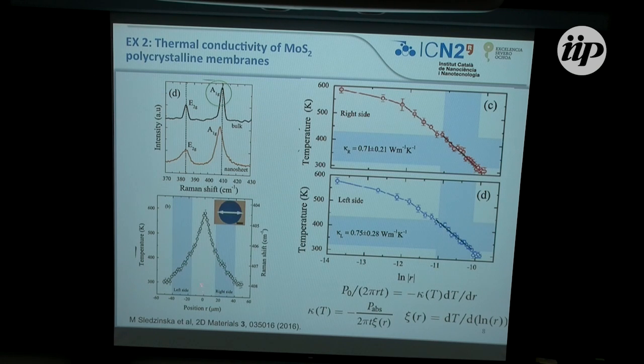And it gives us this temperature field as a function of a point across the membrane, basically going up to about 600 Kelvin, so showing 300 degrees of heating, and looking at the detail of the experimental data on the left side and on the right side. There's a slight difference, which we explain in a funny way, but the bottom line is that the thermal conductivity is around 0.7, 0.75. That is 1/100th of the thermal conductivity in the bulk of molybdenum disulfide. So it's a factor of 2 orders of magnitude reduction.